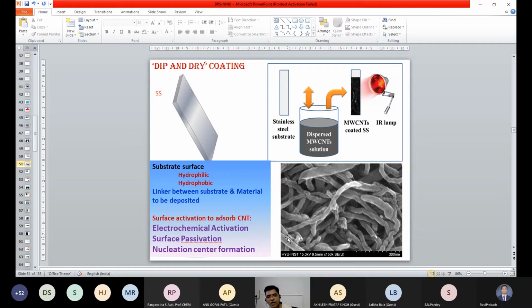So we are also using electrochemical activation, surface passivation, and nucleation center formation, so that you can use simply stainless steel, which can be dipped inside the dispersed carbon nanotube, and then you can take it out and dry it inside the IR lamp. And depending upon the number of cycles, the thickness can be varied. And this is the carbon nanotube coated on the stainless steel substrate.